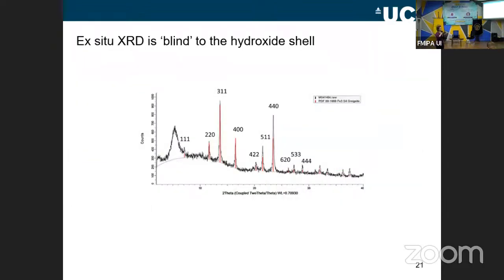The interesting thing is that if you take that sample and you carry out XRD on the sample, so X-ray diffraction, which is a very common technique for characterization of materials to see what's there, all you see is the spectrum for the greigite. So it looks as if it's the same as the starting material. And that's because XRD can only see crystalline samples. So it can only see the crystals in the sample if it's ordered. So if it's a sample which has a crystalline structure in the middle, but on the surface has an amorphous layer, this means that it won't see the amorphous layer. So it can't see that you've got that hydroxide. So it looks as if it's the original material.